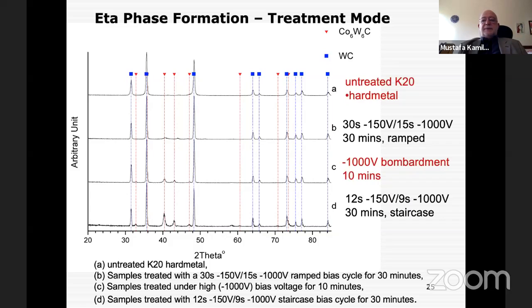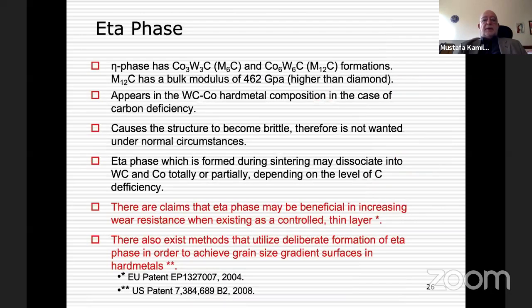Eta phase is this compound. This is a complex cobalt tungsten carbide phase that forms as a result of carbon deficiency in the tungsten carbide cobalt system. And this is normally not a wanted phase in the tungsten carbide cobalt structure because it embrittles the material. However, if this phase only forms on the surface, on the other hand, it is also beneficial for a lot of property improvements, such as hardness increase, better cutting performance, etc.